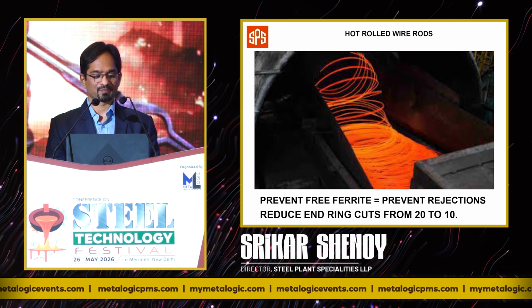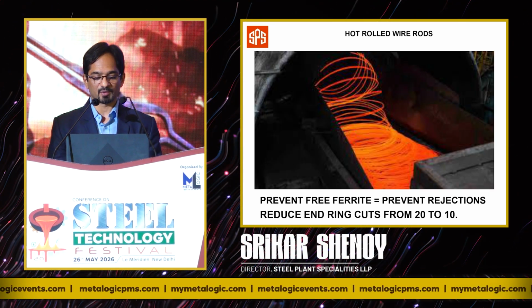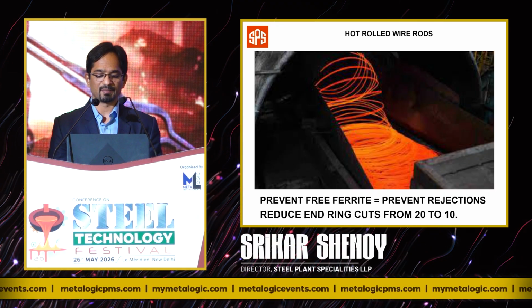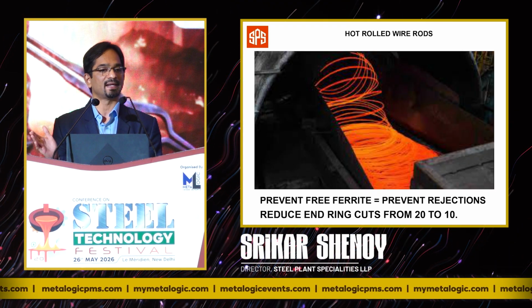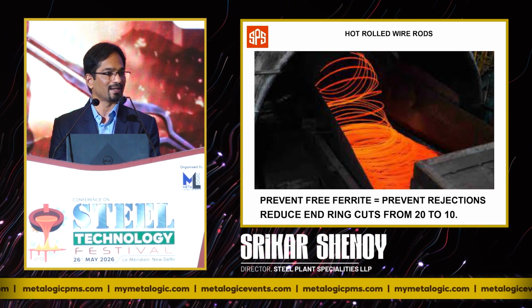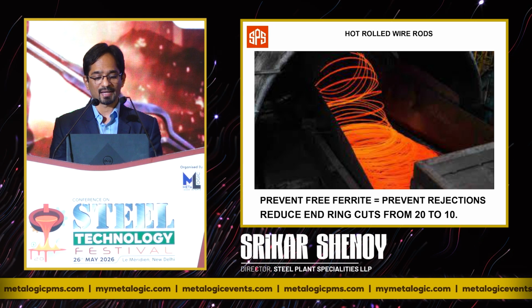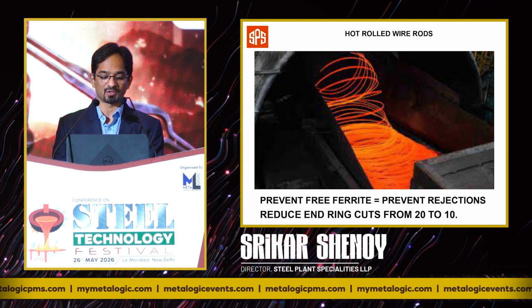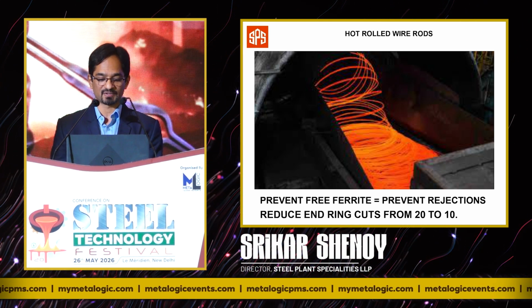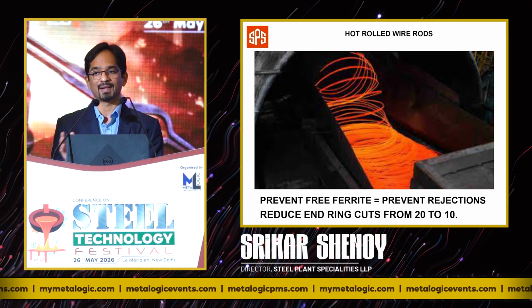End cuts can be reduced right from 20 end cuts to 10, simply because the surface area of edges of billets are more susceptible to scaling and decarb, and that's why wire rod manufacturers have to actually cut 20 ends to get a good surface finish. That is reduced from 20 end cuts to 10.